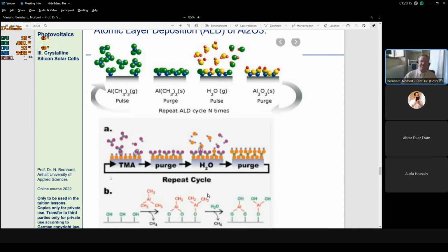It explains the same. That means, you see, this is why this process is called atomic layer deposition, because one has these alternating precursors, and just by this pulse and purge cycle, one can in principle count the atomic layers. That means by this process, you can deposit a certain predefined number of atomic layers.